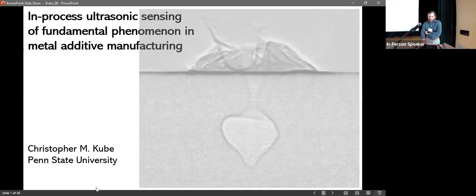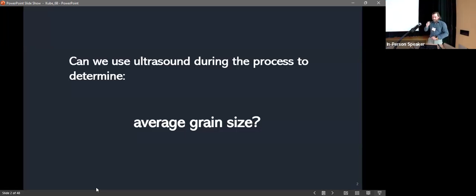There are two different themes here. One is ultrasound integrated into a real process, potentially monitoring the microstructure of the part as it's being printed. The other is melt pool monitoring. The advantage of ultrasound is that it senses the internal volume of the structure. Jay put out several sensing modalities that are primarily sensitive to the topmost layer, so you can see the topmost vantage point of the melt pool, but you can't see underneath of it.